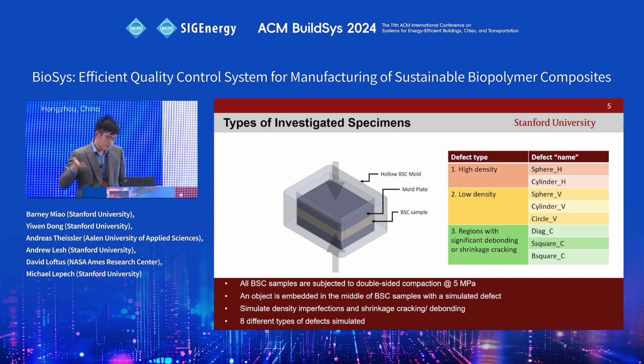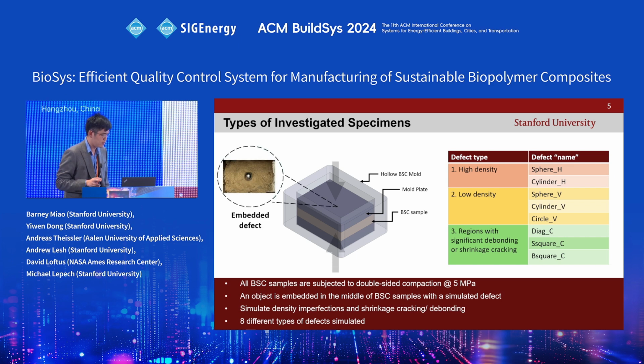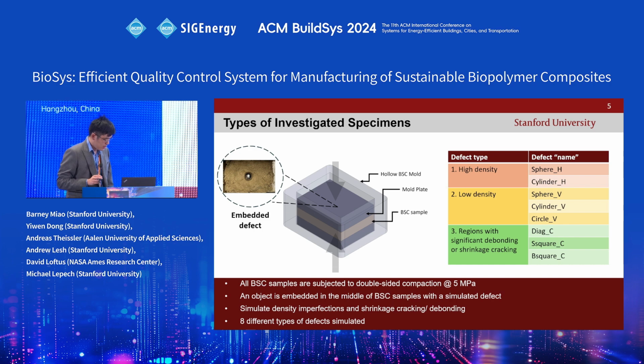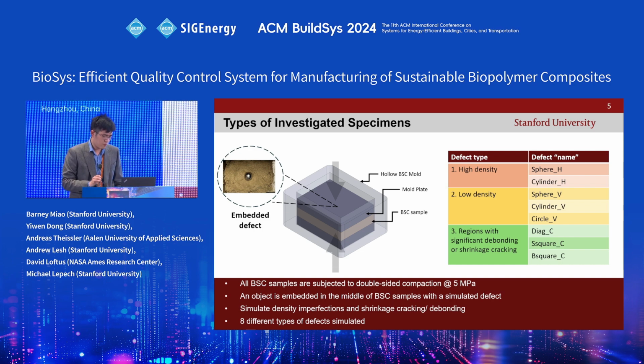In this case, BSC samples are normally manufactured with double-sided compaction. So you imagine you have a sample in the middle, you compact one side, flip it, and compact it again until you reach this stress level. For all these samples, we have the same dimensions, but for the control sample, there's no simulated defect, whereas for the other ones, you can imagine you're embedding or simulating a defect in the middle. And we have simulated some high-density defects and low-density defects.